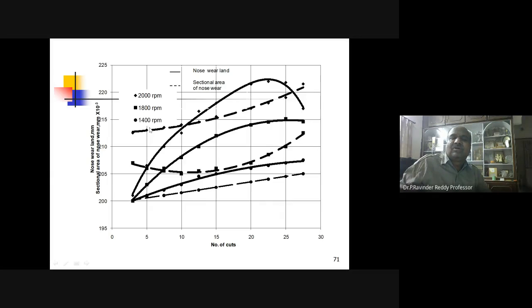And you can plot nose wear and sectional area of the nose wear at different cutting speeds. The cutting speeds selected are 1400 RPM, 1800 RPM, and 2000 RPM, and you can observe that against the number of cuts, when you increase the number of cuts, the nose wear is increasing. But increasing after a certain level, you can observe after this it is again decreasing, whereas the sectional area of nose wear is increasing.